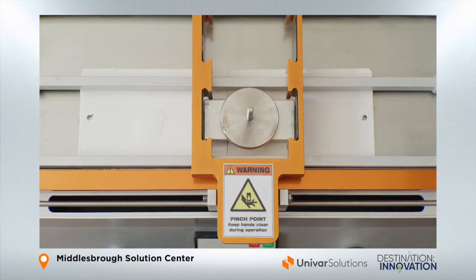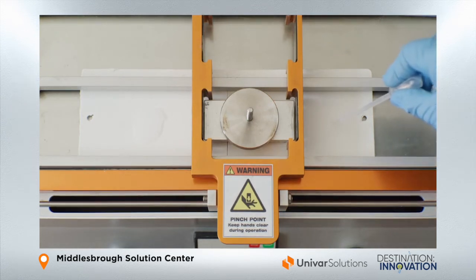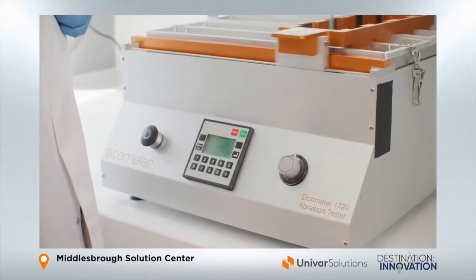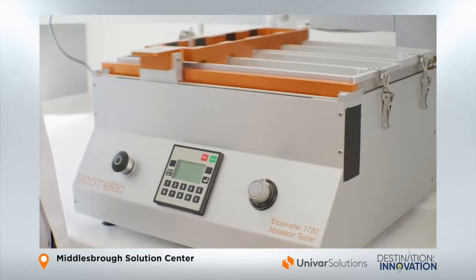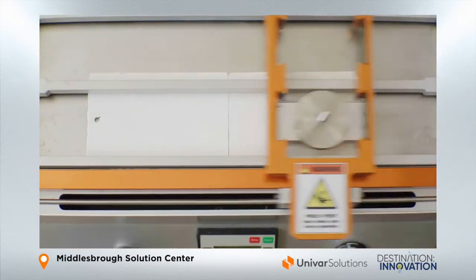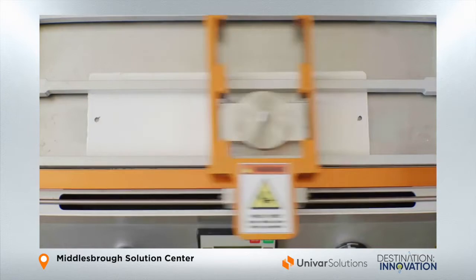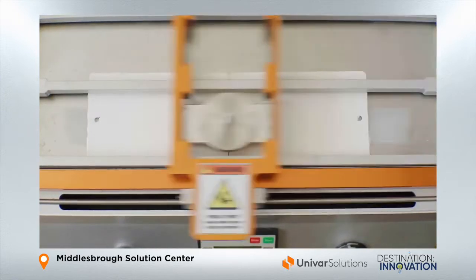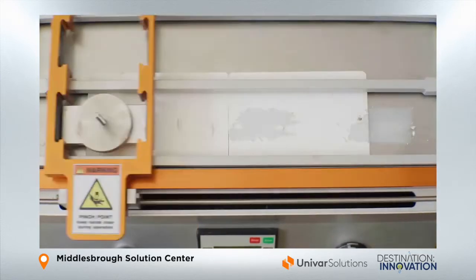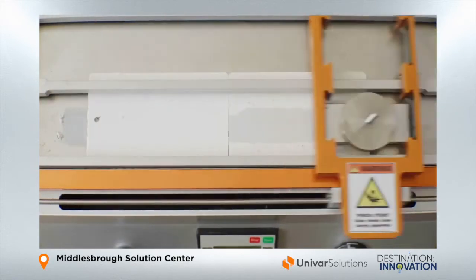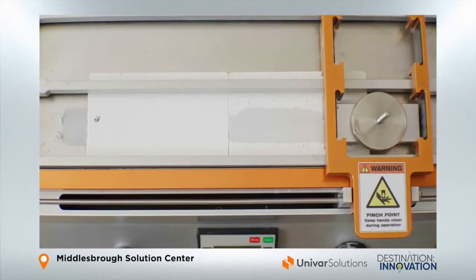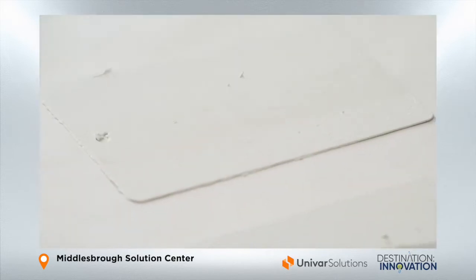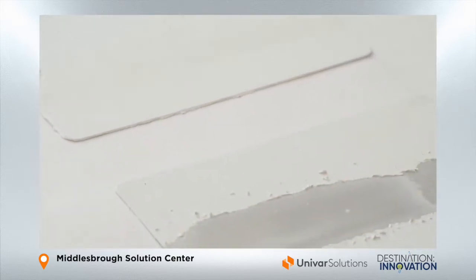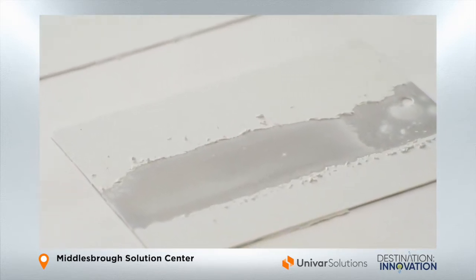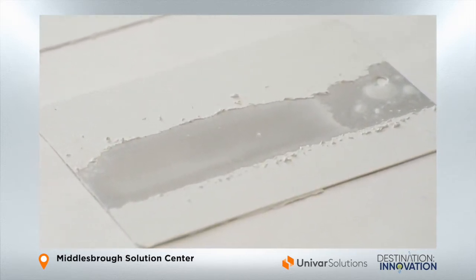For this test, we are going to place water onto the surface, a set amount, pre-weighed. For this, you could also add soap or things like that. You're going to switch it on and allow it to move back and forwards to simulate as if you are scrubbing the wall. And in this video, it has been sped up to show this passage of time. But as you can see, the panel on the right without the silicone additive eventually will begin to break down and remove from the surface, whereas the panel on the left with the silicone additive does not show the issues and shows very minimal damage comparatively. So it would be a lot more durable in terms of being able to clean and wipe in your home paints.